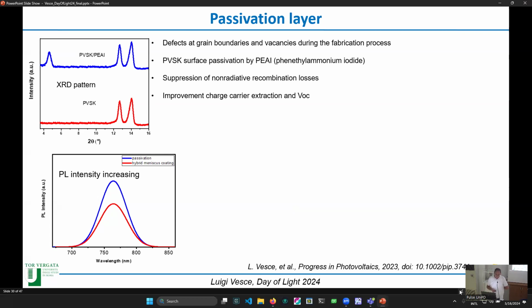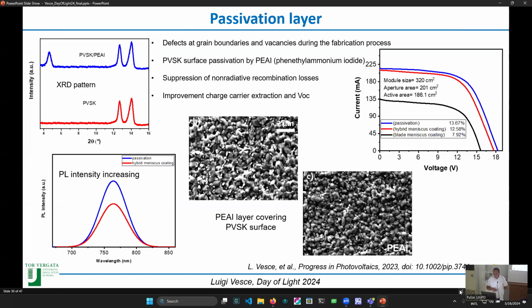So we deposit this passivation layer, the phenylethyl ammonium iodide, that we also used in the past, but by spin coating method. Now we deposit this layer also by the slot die coating method. And by XRD, we can see this peak at 4.7 degrees that testifies the presence of the PEAI. And thanks to this, we can suppress the non-radiative recombination losses and improve the VOC, as you can see from the blue line, with a maximum efficiency of 13.7%. But we want more.